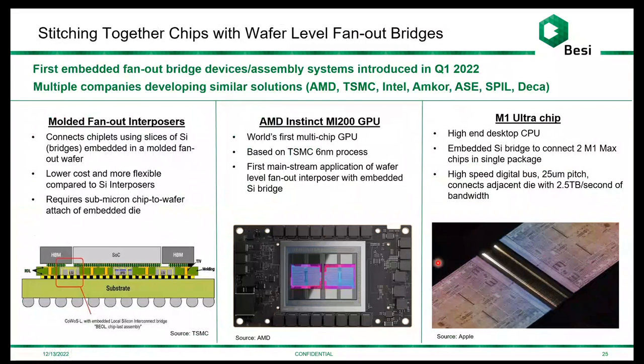A couple of high profile announcements: this AMD product that uses the elevated fan out bridge, as AMD calls it, and then the M1 Ultra also using a similar technology. And basically it allows a very high bandwidth 25 micron pitch interface between chips that are mounted on top of this interposer.